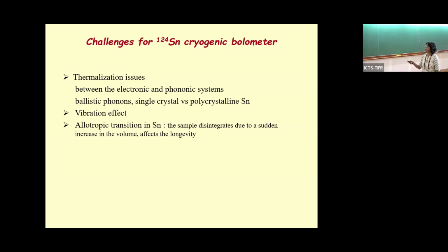So people have also explored single crystal versus polycrystalline, because polycrystal has more boundaries, so there is scattering at the boundaries and so on. But finally, I think this is, right at this point, not very conclusive; which will give better, you will see only when you go to large size. The other important aspect, for all these bolometers, or when you talk of such low energy resolution, low temperature, is the vibration effect.